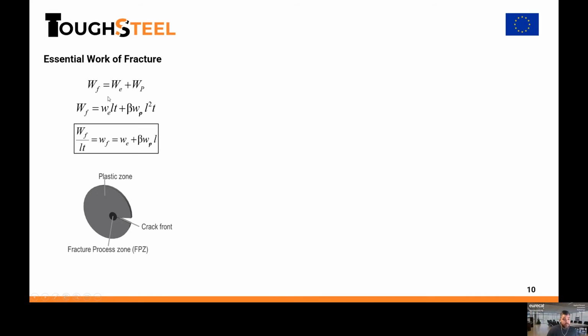As I said, the fracture energy during a ductile fracture process can be split into two terms. One, the essential work of fracture, which is developed in the fracture process zone, which is the fracture toughness itself, the energy to generate new surfaces at the crack tip, and also an extrinsic or outer non-essential plastic work. Remember that I said also that in the J resistance curve, all the points have an extrinsic contribution from the plastic work. So this is the same idea.